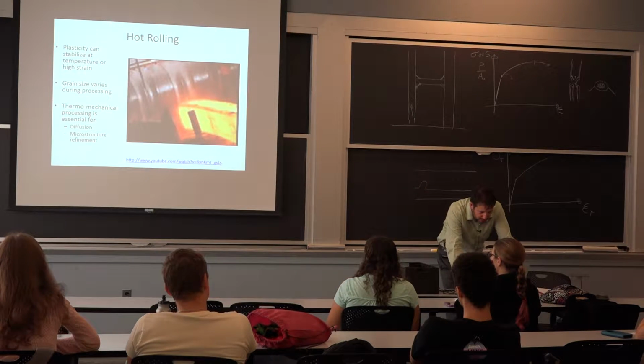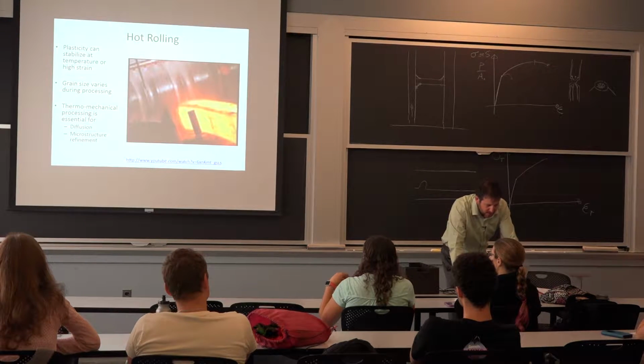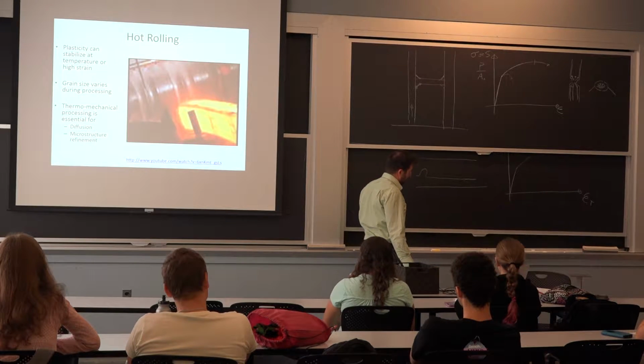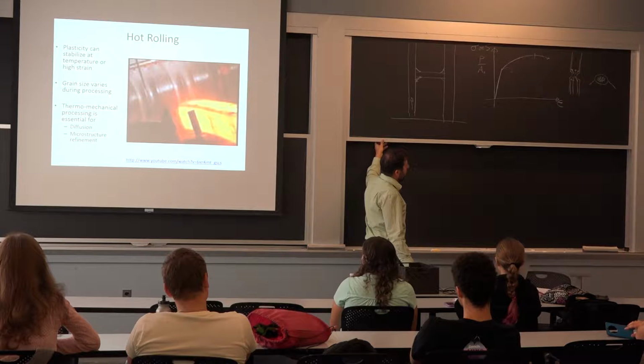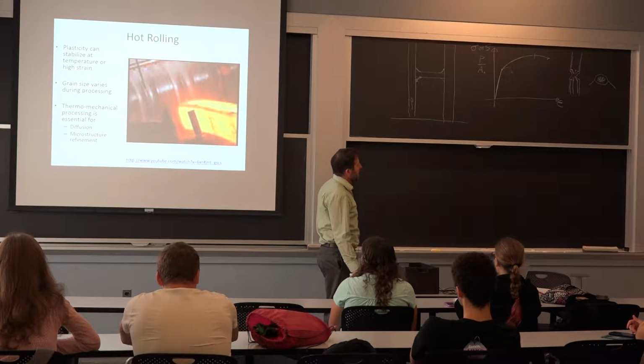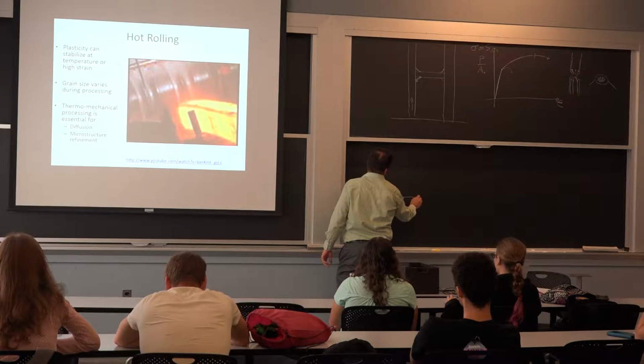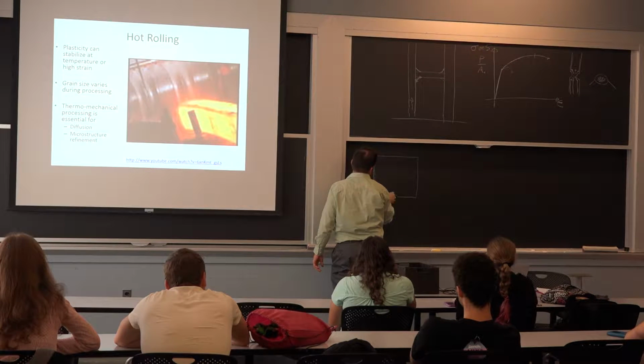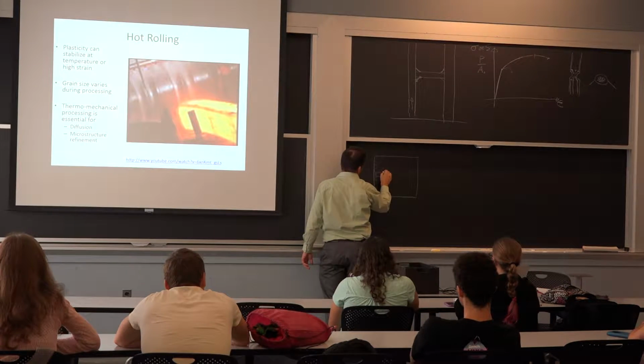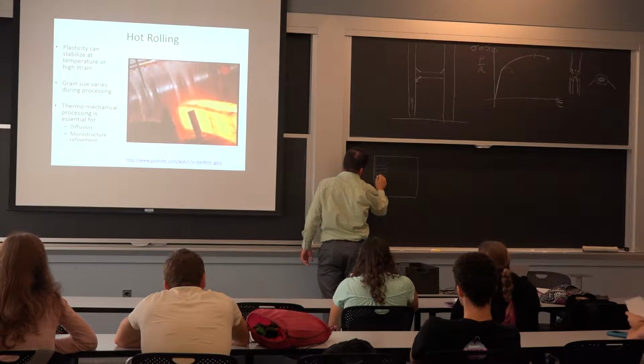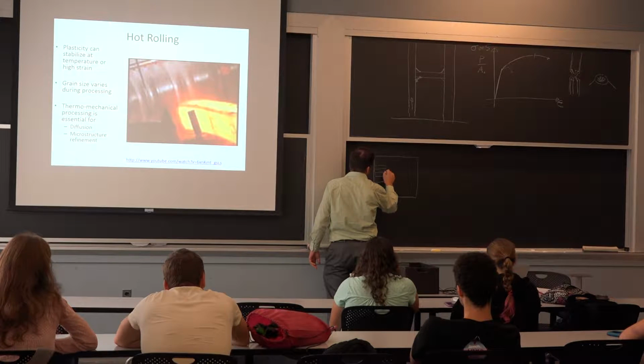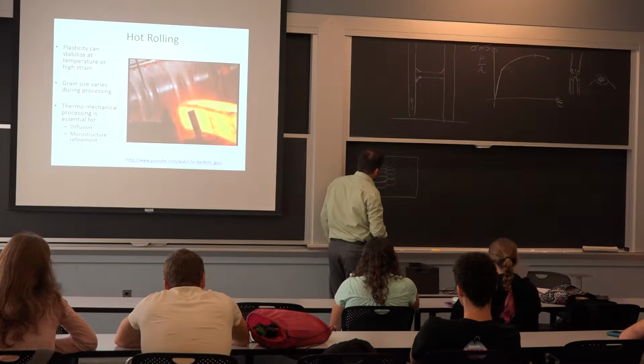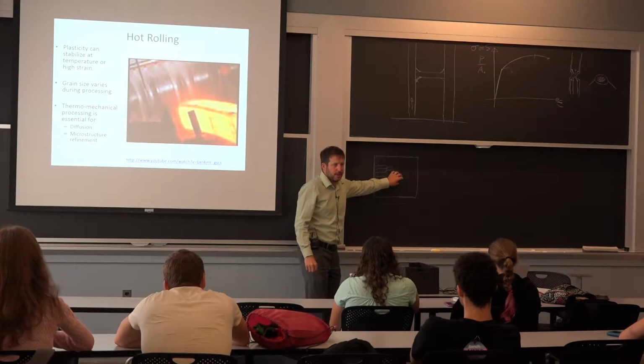Now, what I want to do now is go back to how we roll steel. I think we have all the concepts to do it, and we'll do it on the board. I think we discussed we have the billet first. It's got a little chill zone. Then it has more of the elongated or columnar grains, and that can include the dendrites typically, although the dendrites in a lot of processes do get broken down. So there's nothing to say that it's just one grain. You can have multiple of them. And then you have kind of the center where everything ends up cooling, and that's where you get porosity. That's where you get more concentration of your alloying elements down here.